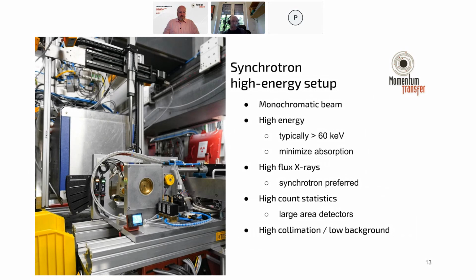We work at very high energies, again, compared to laboratory diffraction systems. With synchrotron powder diffraction, oftentimes 60 keV or more if you want highly penetrating X-rays. So we work at 75 keV, and this allows us to significantly minimize absorption from the sample. As I said, the X-ray flux is extremely high, so that allows for very quick measurements.